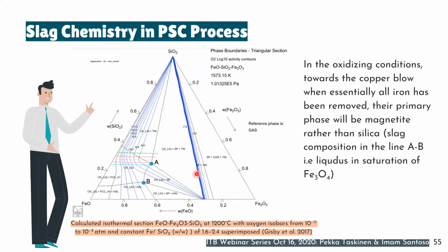Okay, so at the end of the iron blowing or slag blowing, usually the slag composition is a little bit under point A. If the slag is under point A, it is in saturation with magnetite. So before the process moves to the second step, which is copper blowing, the end of slag blowing can be seen by the saturation of magnetite. So usually the slag that describes the end of slag blowing will have magnetite, or be saturated with magnetite. This is the point of magnetite.